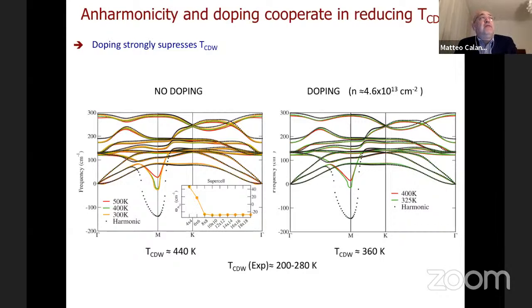So anyway, my feeling is that even in a system where the charge density wave is driven by an electronic mechanism, namely there is the possibility of stabilizing a distorted ground state only keeping the atoms frozen but leaving the electrons moving, even in this case, probably if you relax completely the atomic positions and optimize, you will see that the greatest energy gain is given by the lattice energy gain. So one question is, what is the mechanism that starts the charge density wave? This is difficult to answer in many cases because it's not so clear. Sometimes you cannot completely disentangle the degrees of freedom. But what is probably true is that in most cases, most of the energy gain is given by the lattice relaxation.